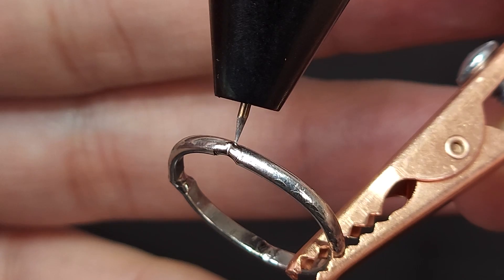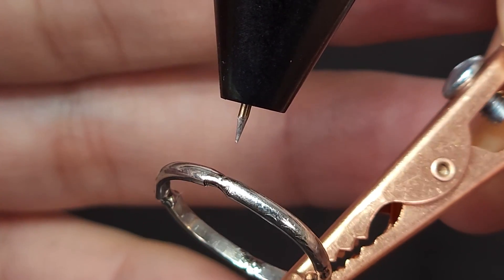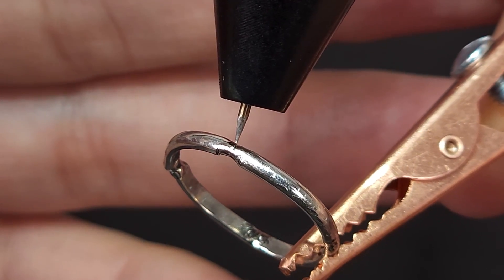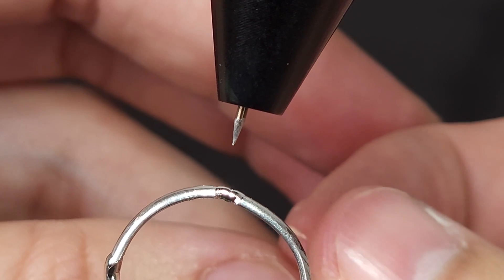Now I'm going to do another weld here. So this initial weld, what I like to do is really light it up because what I found is this particular metal, especially when it's hard or work hardened, it doesn't handle hammering or reworking.